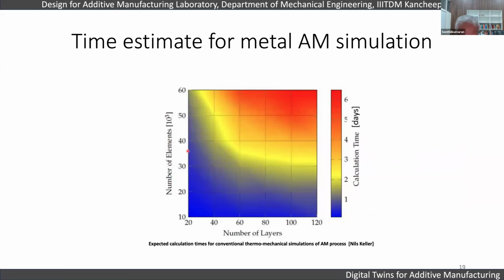Okay, so now I want to give you a very different perspective. When you want to do such fluid flow and thermomechanical simulations for a large-scale part, it is going to consume a lot of time. So there has been a lot of effort in the past to reduce the time and do faster prediction. You can see this is one of the expected calculation times in terms of number of elements. If you have a number of elements around 60,000, you can see that it goes up to 6 days, for a layer of 120. So for a 20 layer part, it goes up to even 4 days to get the result. You can see this for each individual layer.